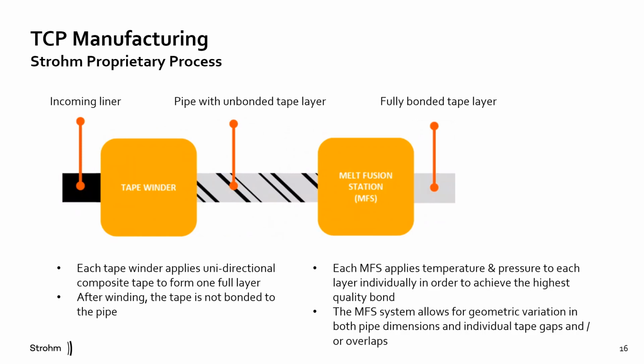From here, the tape is then fed into our MFS, where our proprietary system applies just the right amount of temperature and pressure to create a fully consolidated layer. This process is repeated over and over until we have reached the desired thickness of laminate to give the pipe the performance that it needs. We also have the freedom to change the angle within any individual layer in order to tailor the pipe cross-section properties for specific applications such as riser systems. Regardless of this change, the process remains exactly the same, and we arrive at the end with a fully bonded cross-section tailored to your need.